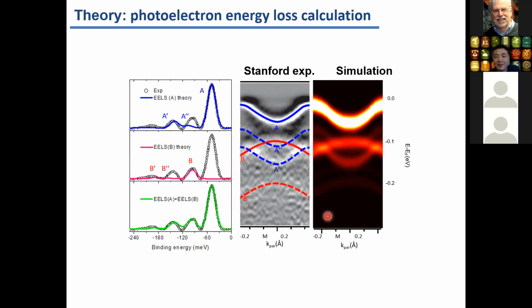So their paper basically provides an alternative explanation for the replica bands observed in the experiments. I want to make a note here that they didn't rule out phonon-electron coupling in these materials. What they propose is that these replica bands in the ARPES may just come from an external energy loss process when the electrons escape, instead of intrinsic phonon-electron coupling inside the iron selenide. So again, they didn't rule out the possibility that electron-phonon coupling is actually very important for this material.